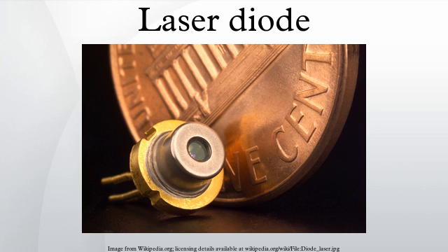Since then, various other refinements have been employed. One approach is to create a so-called non-absorbing mirror such that the final 10 micrometers or so before the light emits from the cleaved facet are rendered non-absorbing at the wavelength of interest. In the very early 1990s, SDL Incorporated began supplying high-power diode lasers with good reliability characteristics.